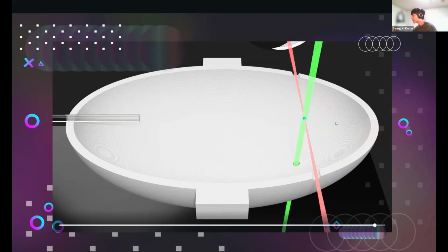So it's easier to make a small crystal than a large crystal with a single defect, right? Actually, it's a little bit easier to make a large crystal with a single defect. For example, ion implantation is the canonical way to do it in a larger crystal. I can make an implantation mask and poke a small hole in it, and then only the ions get in through that small hole. Basically, I know that small area will have single color centers.